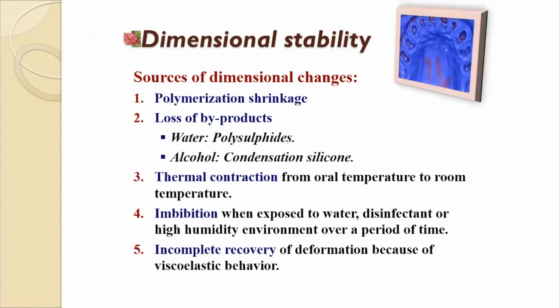Then coming to your dimensional stability. So your dimensional stability would depend on your polymerization shrinkage, loss of byproducts like water in polysulfides, alcohols in condensation silicones. Then thermal contraction from oral temperature to room temperature happens. Then imbibition. Imbibition means when exposed to water, disinfectant, or high humidity environment over a long period of time, it absorbs the water. So this you have to keep in mind, that you do not have to soak it in water for a very long period of time. You do not have to keep it immersed in a disinfectant for more than 10 minutes. So this I would just discuss.